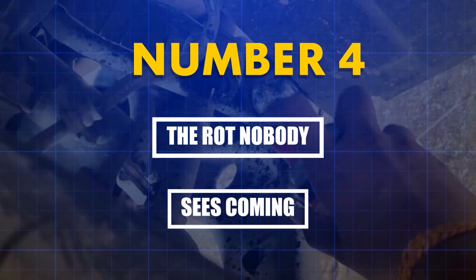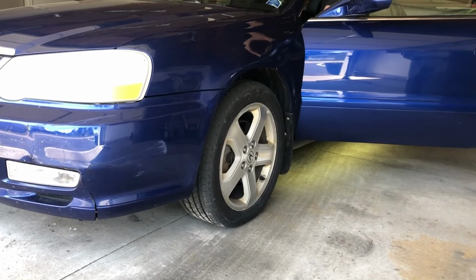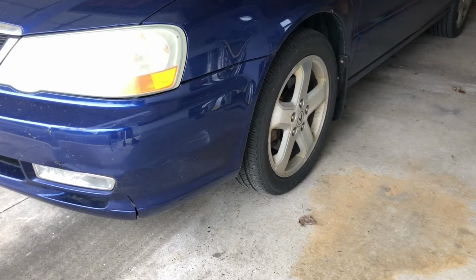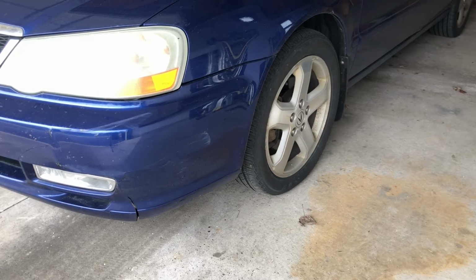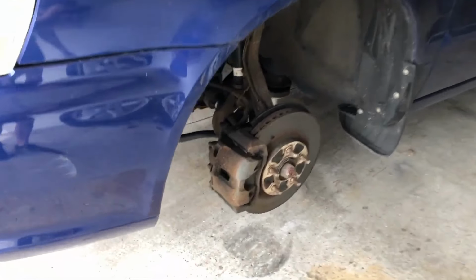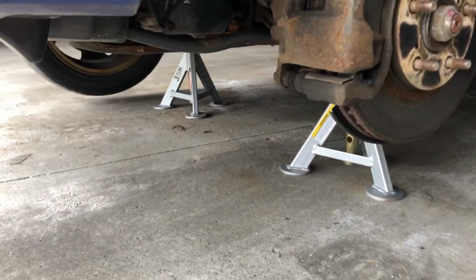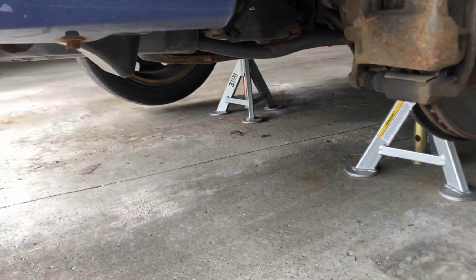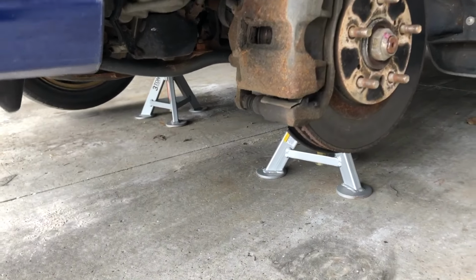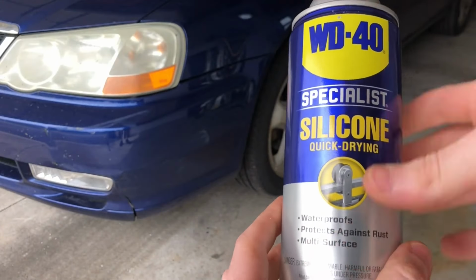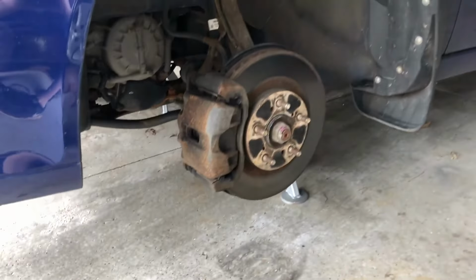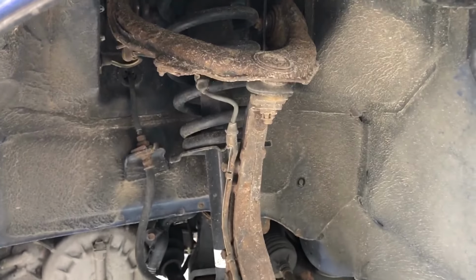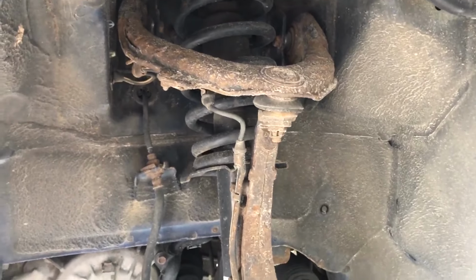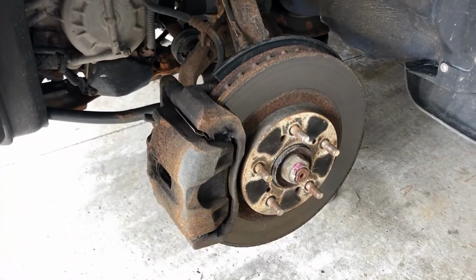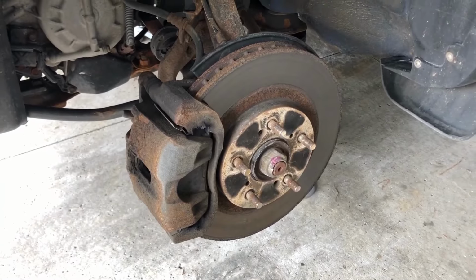Trick number 4, the rot nobody sees coming. Rust starts silent. Under your car, moisture meets bare metal in the dark. 3 months later, at highway speed, a suspension bolt snaps. I've seen it. Not dramatic until it is. After every wash, get under there. Spray WD-40 on exposed metal, suspension arms, subframe bolts, jack points. That hydrocarbon film blocks oxygen and water, the only 2 things rust needs.